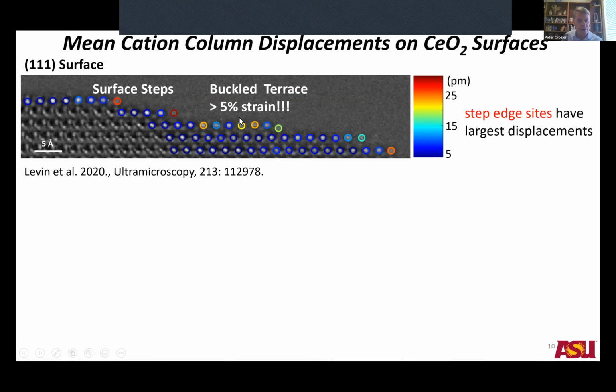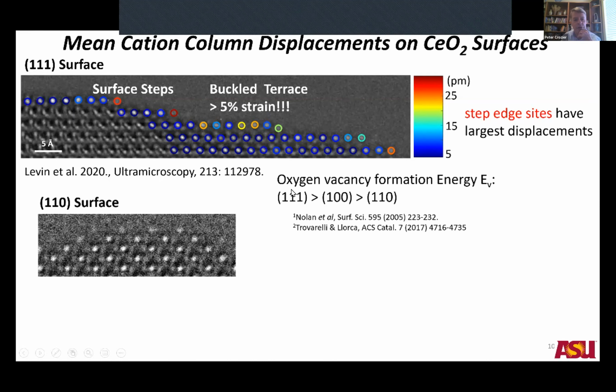But there's lots of other interesting things. For example, if you look carefully at this terrace here, this terrace is actually buckled, and you can see that there are pretty high displacements taking place on this buckled terrace, which would again be indicative of oxygen vacancy creation and annihilation. And in fact, if you go to the density functional theory, you find that the oxygen vacancy formation energy on a 1,1,0 surface is actually much smaller than the vacancy creation energy on this 1,1,1 surface, which is predominantly what we have here.